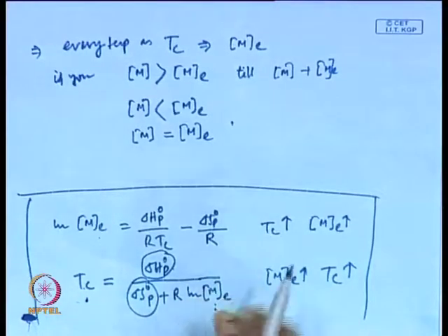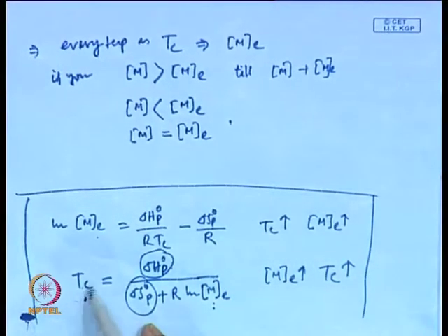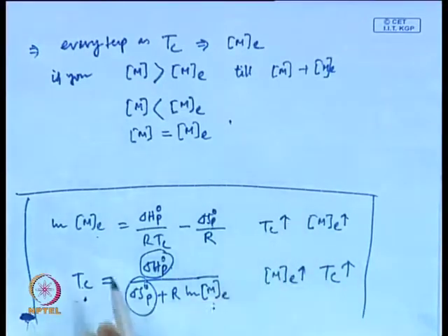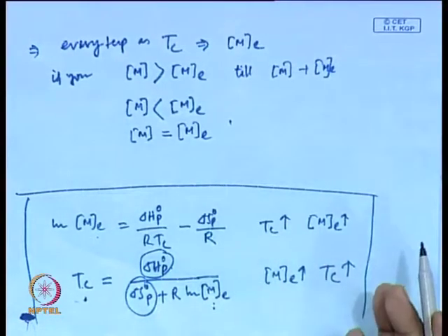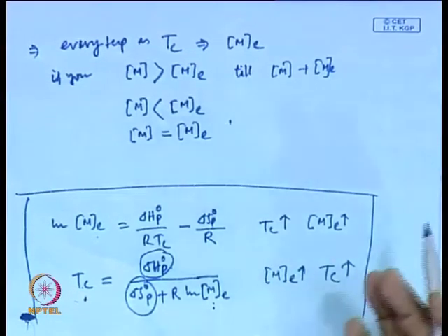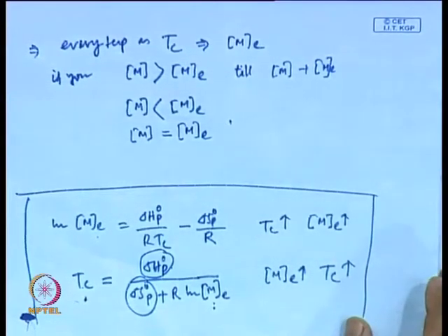Okay. Which means that for a pure monomer, Tc is much lower for alpha methyl styrene compared to styrene, which means that alpha methyl styrene cannot be polymerized, whereas a molecule like styrene can be easily polymerized to a very low equilibrium value of free monomer in the mixture.